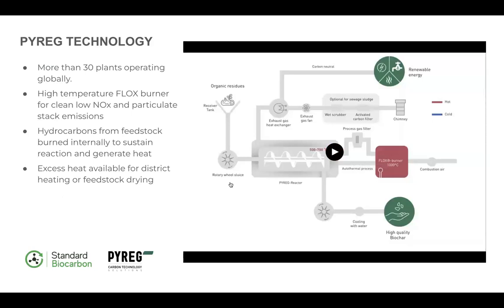So now I'll get a little bit more into the pyrolysis technology that we will be using, the Pyreg PX1500, as I mentioned. It's a top of the line equipment manufacturer, and they've got a pretty good track record of units running over in Europe. I'd say that the most unique feature of this pyrolysis unit is the high temperature flox burner, or the flameless oxidation burner that will recycle and burn the hydrocarbons that are emitted from the feedstock as a green energy heat source for continuous biochar production. This is basically like a highly efficient biomass boiler. It's so clean that it doesn't even need a scrubber. It just takes those emissions off the wood chips and makes the pyrolysis process autothermal.